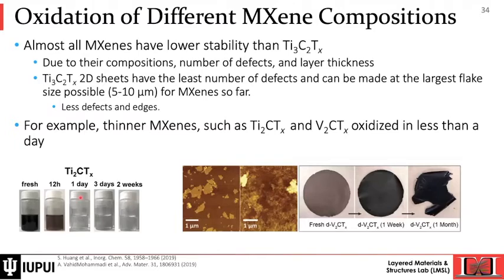If we work with other MXenes, because they have smaller flakes, they have more defects, and we have not really mastered the synthesis route of other MXenes, they're more defective, and some of them are thinner, which means that they will be oxidizing even faster. Here's a Ti2C. After 1 day in colloidal solution, it is gone, oxidized and gone. Here's a V2C AFM that you see that after storage, the flakes will turn to oxide.